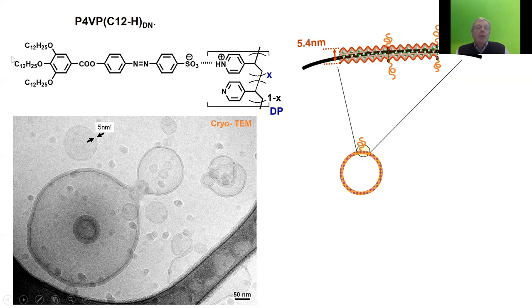This completely unnatural vesicle was formed from a linear polymer with side chains which attached to the polymer by ionic interaction or by base-acid neutralization. So the backbone is hydrophilic, the side chains are hydrophobic, and what you see here is that they form beautiful vesicles. They not only form beautiful vesicles, the vesicles have exactly the thickness that lipid vesicles have.